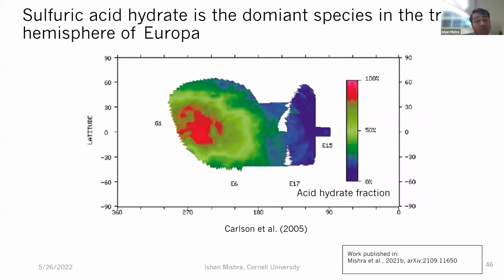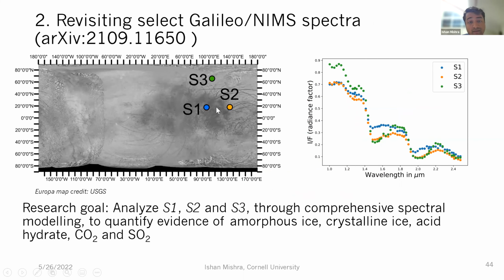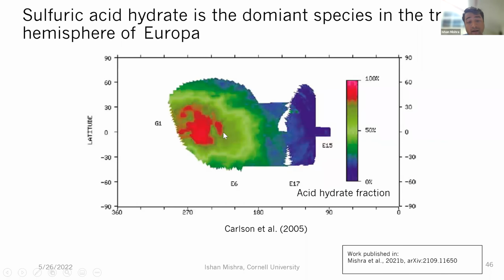So sulfuric acid hydrate, as I was mentioning, in a very early analysis in 2005, people were just trying to fit the data with one kind of water ice and sulfuric acid hydrate. They created this map of the trailing hemisphere of Europa. They found that the sulfuric acid hydrate abundance correlated very well with the dark parts of Europa. So you can see this dark region specifically with this tail kind of feature is also seen in the high acid hydrate abundance distribution from the older work. So yeah, there was one other previous work that had seen evidence for this.